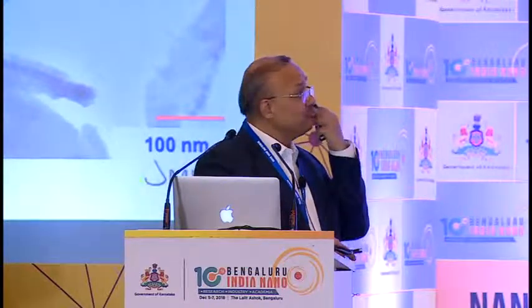So we thought about doing something in that direction. And something came to our mind, polypyrrole. We know polypyrrole, non-processable material, very highly conducting, very stable. You mix it as particles, nothing happens. The blends are really non-conducting. So we thought of creating nano rods out of polypyrroles. There are literature studies on how to create them, and we have successfully created them using certain methods and modifying them. And then came the question whether we can add only 0.01%. Obviously not. We need to add more. So we have to scale it up.